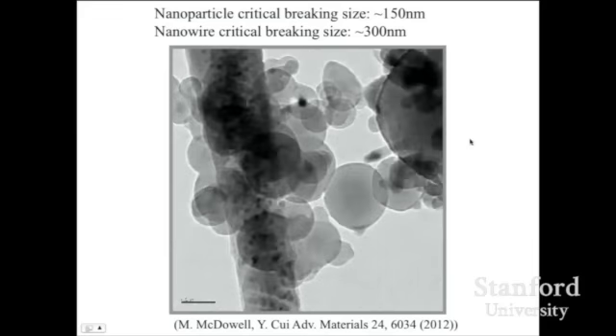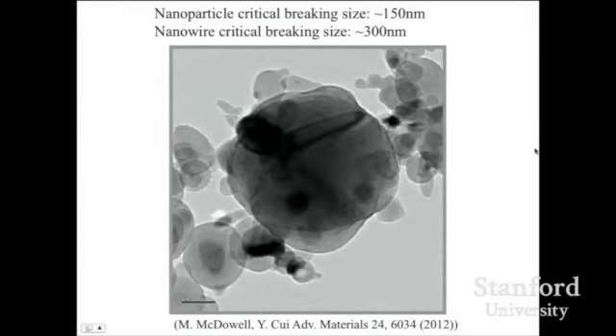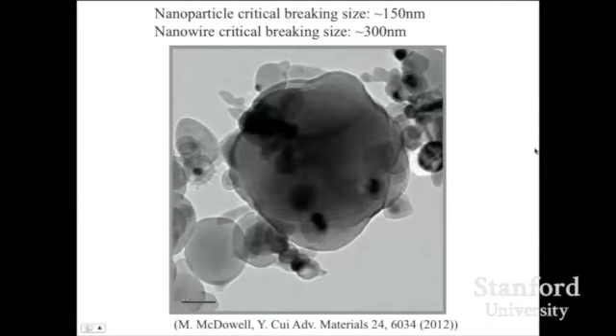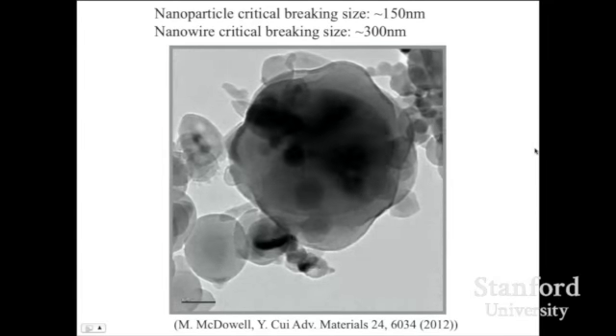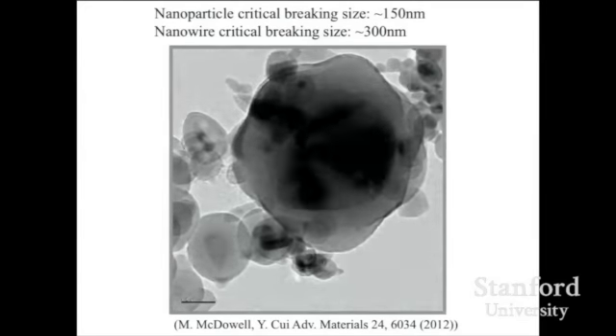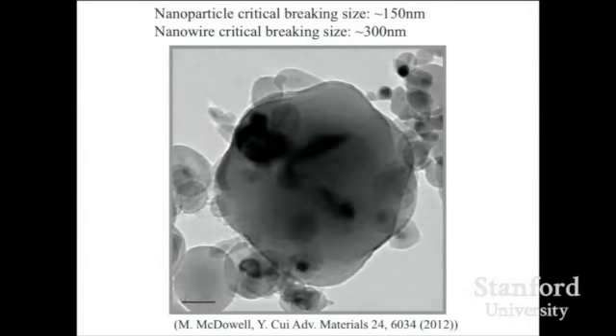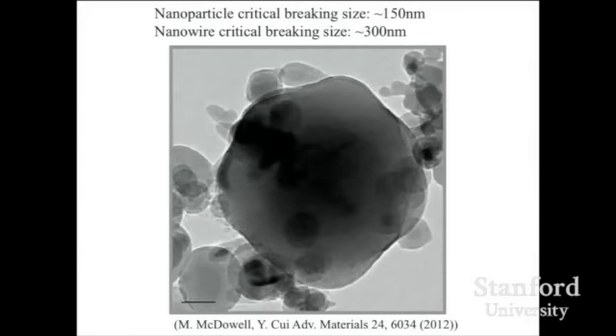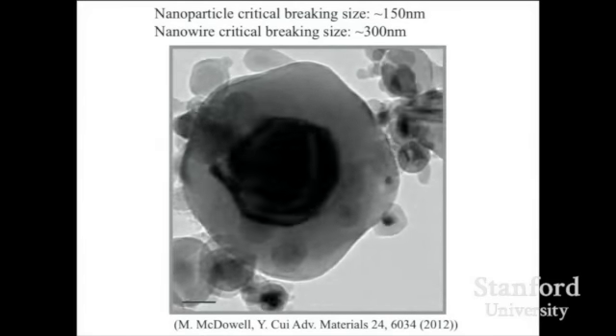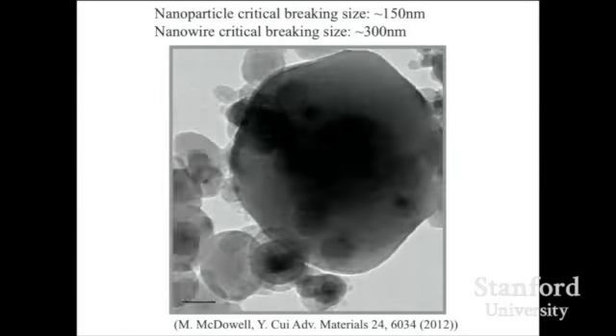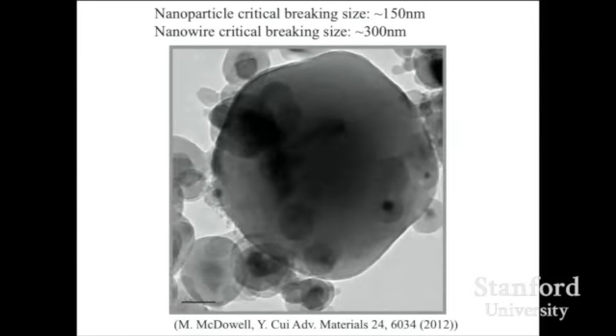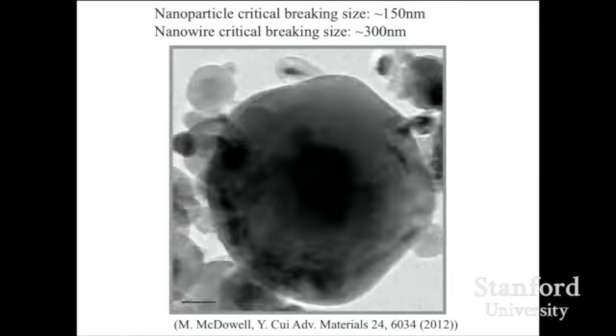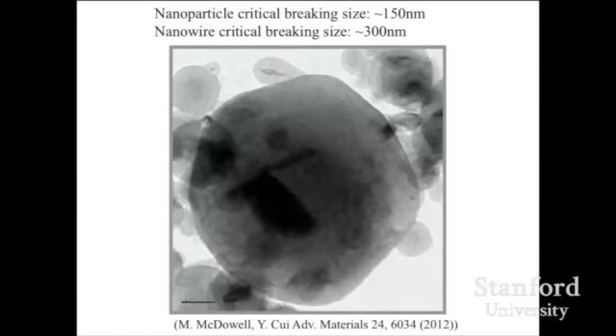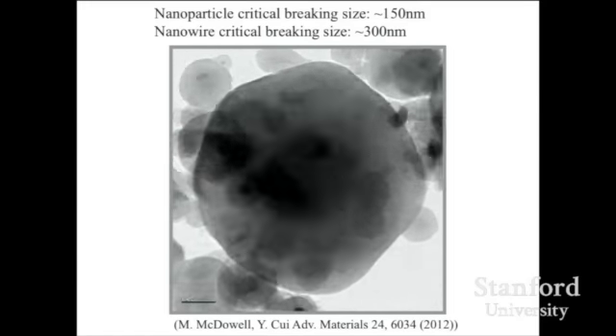Here we go. This is 200 nanometer scale, but also this is a big guy, a big particle. Now you see lithium comes in, crystalline silicon interface is shrinking. This is expanded. This particle is struggling because of this huge stress build up. At some point, it just cannot hold those stresses anymore. You start to see it's going to pop open suddenly.